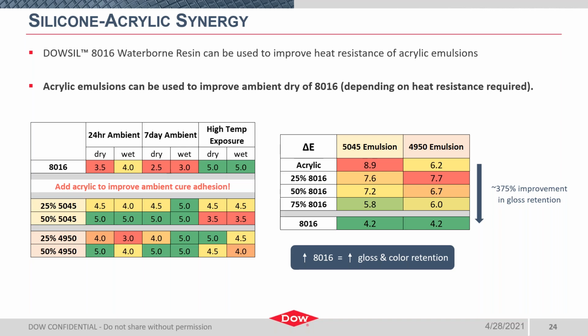So the top row is 8016, followed by 25 and 50% replacement with the 5045 emulsion. And the last two rows are 4950 modification at the same 25 and 50%. And in both cases, when just 25% of that silicone binder was replaced with the acrylic emulsion, the 7-day ambient dry formulation showed much better dry and wet adhesion without surprisingly drastically compromising the post-heat adhesion. So this further allows us to broaden our reachable application space now that we know that spectrum of silicone acrylic performance.